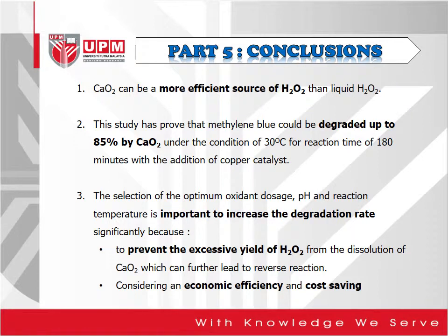As for the conclusion, calcium peroxide can be a more efficient source of H2O2 than liquid H2O2. This research has proved that methylene blue could be degraded up to 85% by calcium peroxide under the condition of 30 degrees Celsius for a reaction time of 180 minutes with the addition of copper catalyst. The selection of the optimum oxidant dosage, pH and reaction temperature is very important to increase the degradation rate significantly, because it prevents the excessive yield of H2O2 and considers economic efficiency and cost saving.